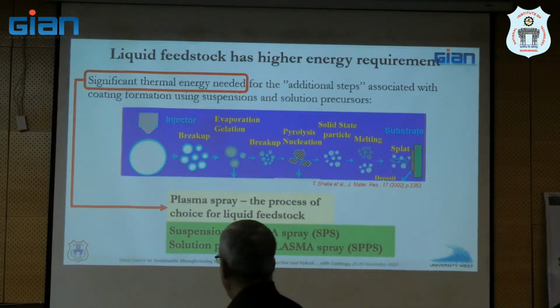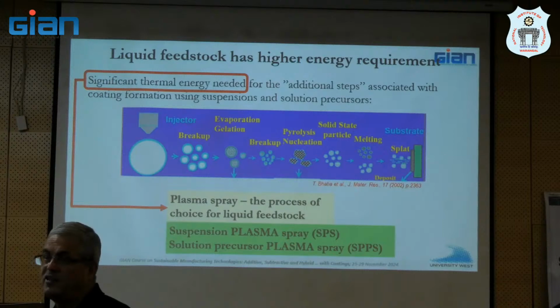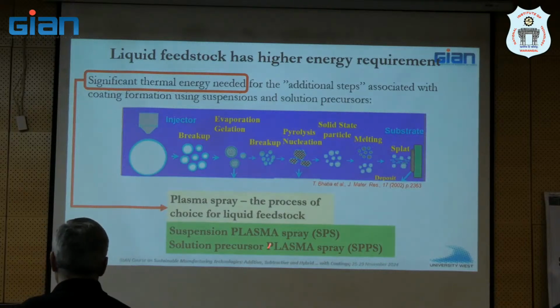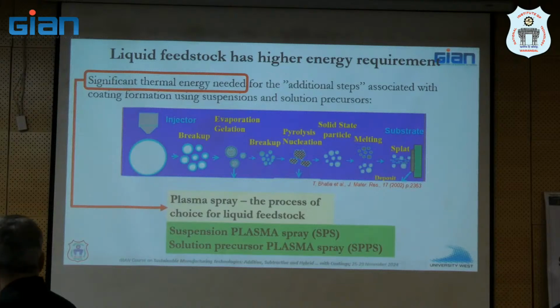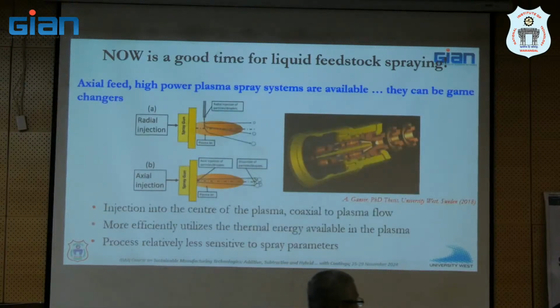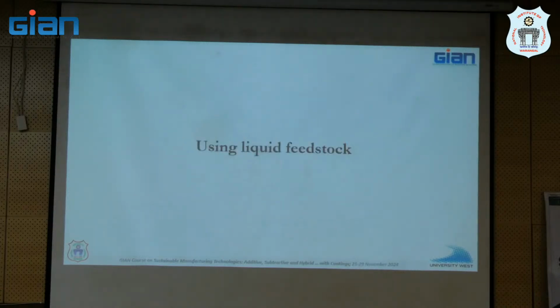So if you look at literature today, you will mostly see these terms used. Suspension plasma spray. You will not see suspension HVOF spray or something like that. I mean, you will see some literature, but not so much. Same with solution precursor plasma spray. That is because plasma is ideally suited to provide the thermal energy that all these reactions need. On top of that, now you are able to feed this feedstock axially through the center. So people who were disappointed or unsuccessful with using liquid feedstock earlier now suddenly can consider going back to liquid feedstock and get some very interesting results. And I will show you some of those.